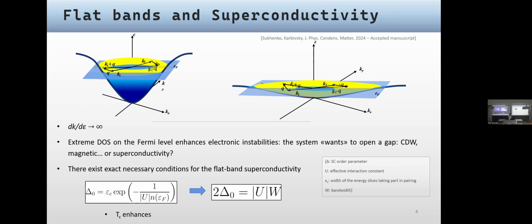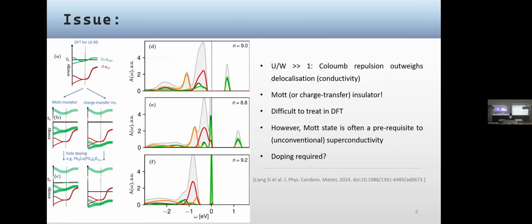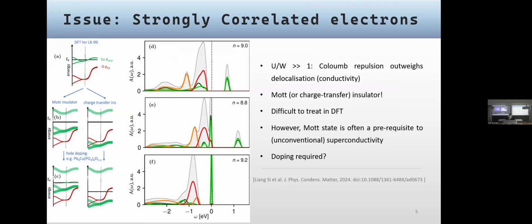And from the BCS theory, it follows that in the limit of a flat band, the superconducting gap value should increase, meaning that with a given attractive interaction, the dependence would be such that it wouldn't be exponentially suppressed anymore. And the critical temperature is usually a monotonic function of the gap, and therefore the critical temperature should also be enhanced in principle. Yes, that's all fine and well, but then first I should remind you what the issue was,